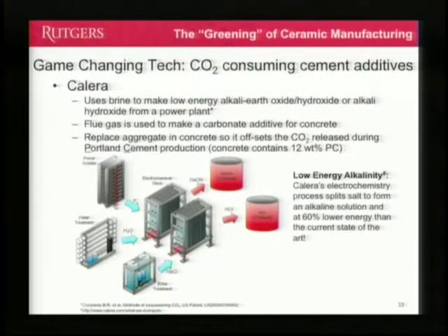And so that gives them the excuse to make, once again, sodium hydroxide, which their selling point is, hey, we figured out how to make it 60% more energy efficient, but it's still sucking energy out of the power plant, and that's one of the problems. The other thing they're doing that's nice, though, is they're using brine from reverse osmosis for their source of cations. And then ultimately they're making this carbonate salt, which is the additive for concrete. So this is another way to kind of get around being green by finding some way of replacing something that can make the whole process appear carbon negative, because you're storing the carbon in the process of doing this.